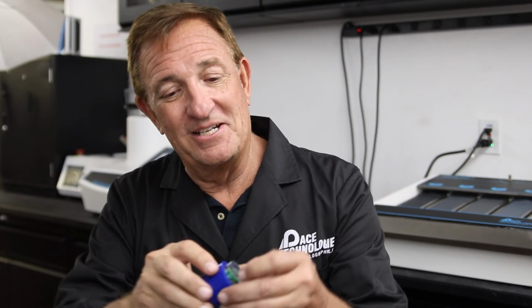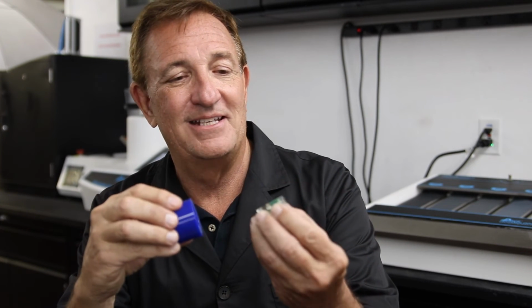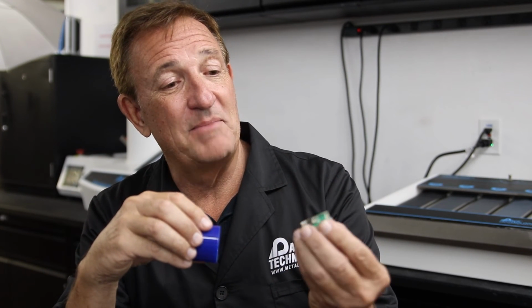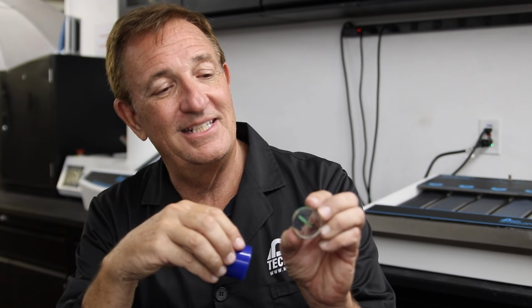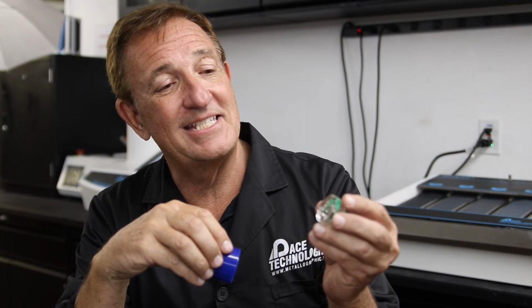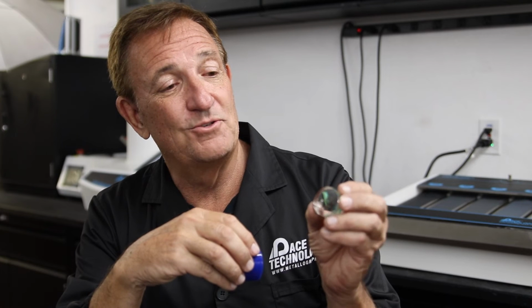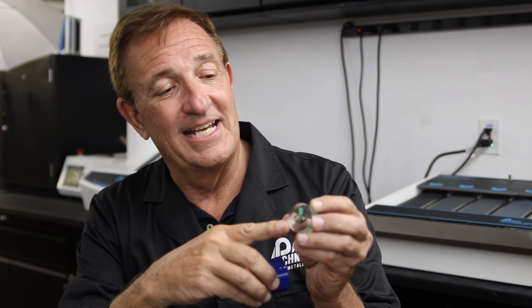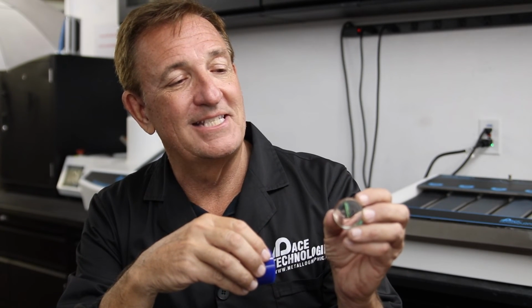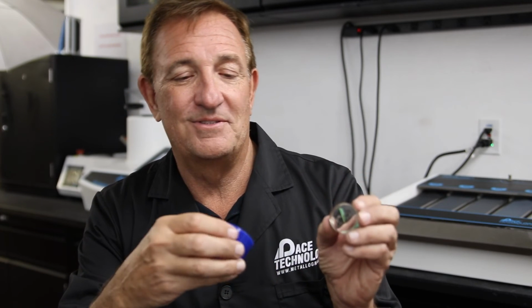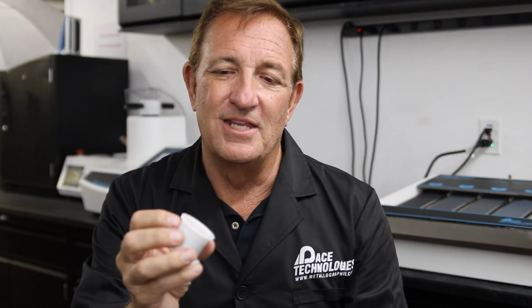Let's take a look at the samples that we mounted up here. So this particular sample here, we have a silicone rubber mold. Pull that out. It's actually a very nice looking mount, especially the ultra-thin. It's a low temperature, low viscosity mounting compound, so it has low shrinkage. It also flowed very nicely into the sample. It's also very clear. And you see this is a flexible silicone rubber here. The other one we have is our two-piece molds.